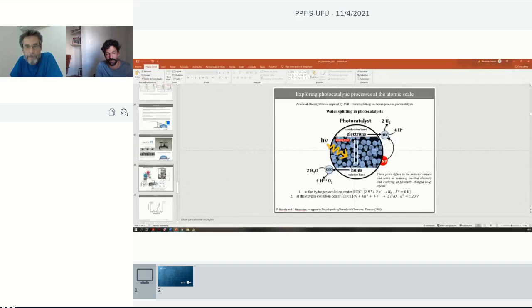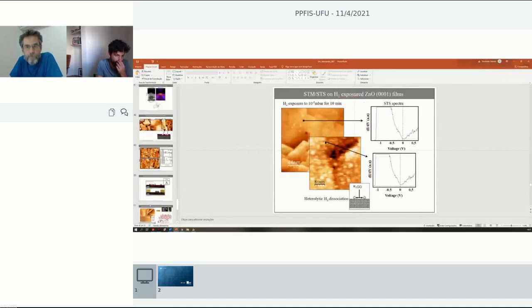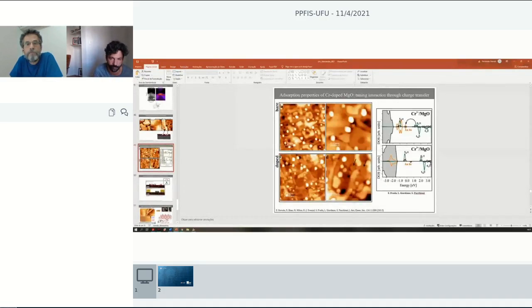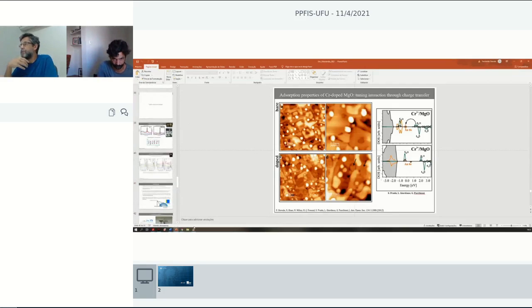When we would like to modify the oxide with doping, I can show you, for instance, this kind of example here that I worked on before, and we still publish things in this direction, where we really have a flat surface. Here it's MgO, not manganese, magnesium. And then you can decorate with gold particles or silver particles and see how the particles evolve and how they change the electronic structure. But that was not the subject of the manganese oxide so far. So the nanoparticles do indeed have, they are small enough that they have an electronic structure that is quite different from the bulk or a thin film or something like that, right?